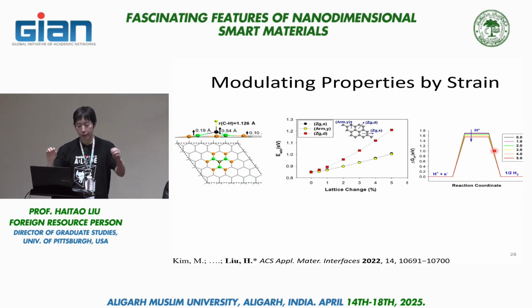To understand this, the model we use is thinking about the hydrogen reduction process, and a key step there is the adsorption of hydrogen atom being a critical intermediate step. So what you have here is a model where we have a graphene surface, and the hydrogen atom would adsorb onto the surface, interacting with one of the carbon atoms. And the adsorption of hydrogen atom to the surface would lower the energy of the hydrogen atom. So this is a known mechanism called hydrogen evolution reaction.